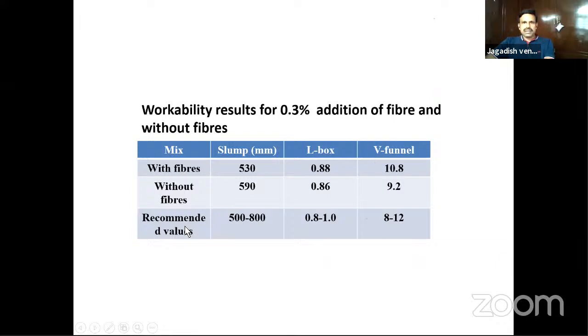Next, you can see the difference between with and without fibers in the flow. Very important: when you add the fibers, more surface area is involved and the flow automatically reduces. That means there is a little dip in the flow. You can see it in the L box, V funnel, and slump. So in slump flow itself, because of the fibers, the spread drops down by 60 mm.